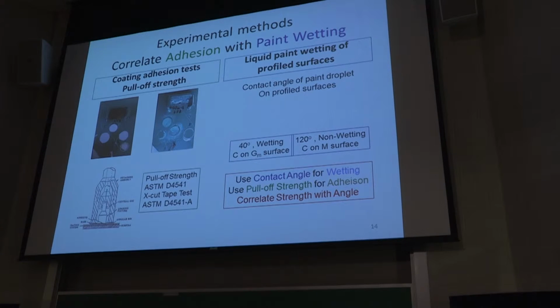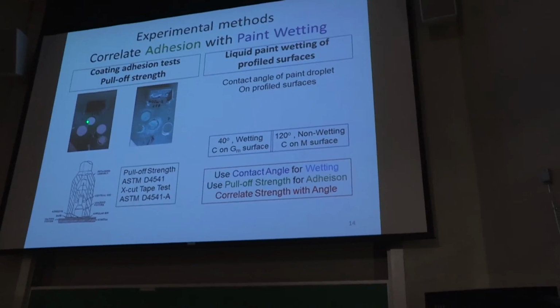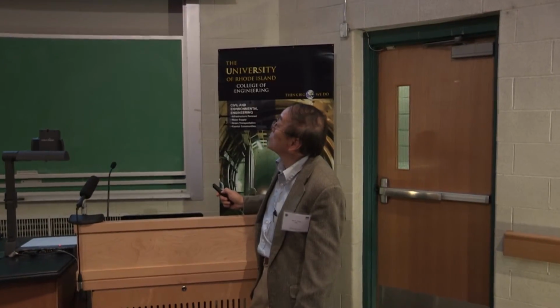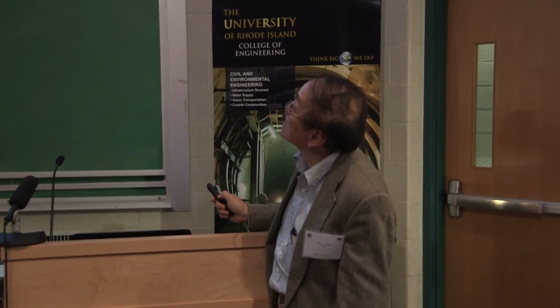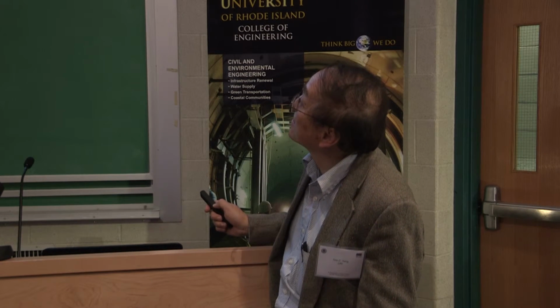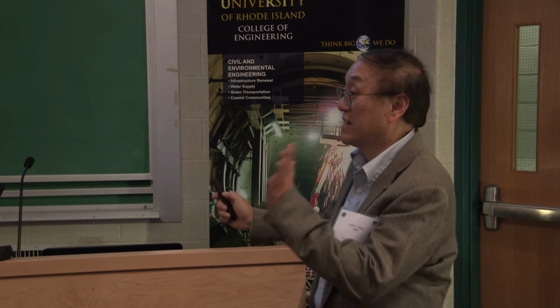Once it's pulled off, we examine which layer is being removed. If all the paint is removed, like in this case, you see the bare zinc in there. That is a weak adhesion. The strength will show it's weak, and we are also able to tell which interlayer is the weak spot. Now this is a good adhesion. We pull it off, and only part of the top paint gets removed, and the underlayers are all intact. And usually this has a very high pull-off strength.